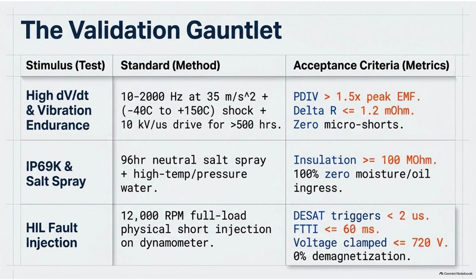And what about the environmental sealing? How do they prove the helium test actually translates to the real world? The document mentions an IP69K test. The IP69K test is the ultimate intrusion standard. They take the motor and subject it to 96 hours of constant, highly corrosive neutral salt spray to attack the metals and seals. Immediately after, they hit it with a high-temperature, high-pressure water blaster. We're talking 80 degrees Celsius water at 100 bar of pressure, sprayed from every angle. Like a supercharged, boiling pressure washer point blank on the seals.